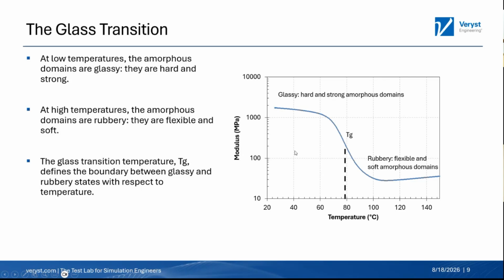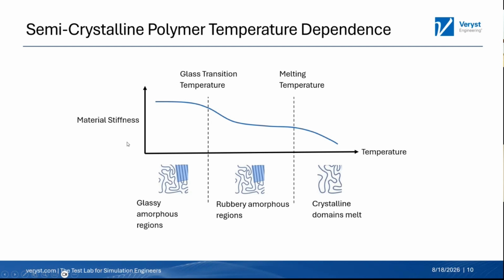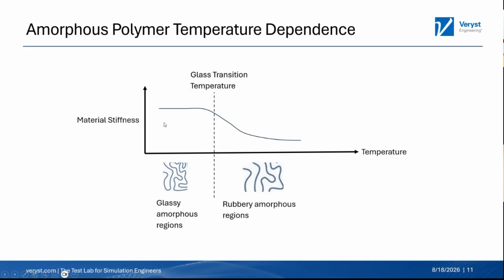And so as we step through, this is the way I, in cartoon form, reduce the thermomechanical behavior of polymers to one cartoon, which is as we think about the material stiffness versus temperature, at very low temperatures, for semi-crystalline polymers, we have glassy amorphous regions because we're below the glass transition temperature. Those amorphous domains are rigid. As we go through Tg, those amorphous domains become rubbery, but we have those crystalline domains still. So we still have a reasonably high modulus. As we go through the melting temperature, those crystalline domains melt, and we have a very, very soft material, a viscous fluid in some cases. In contrast, for amorphous polymers, this diagram looks a little bit simpler because there's really only one transition. As we go through Tg, we go from glassy amorphous domains to rubbery amorphous domains. So we're going from a harder material into this softer, more rubbery material.